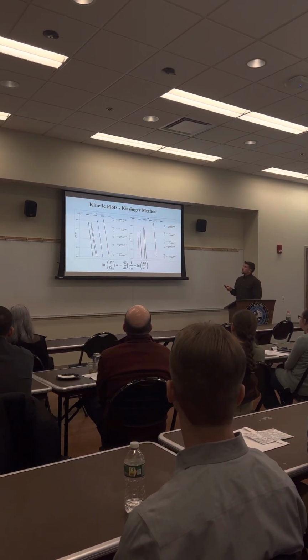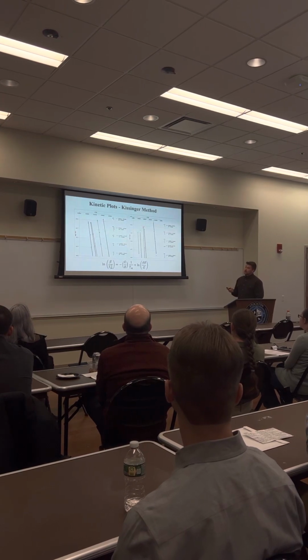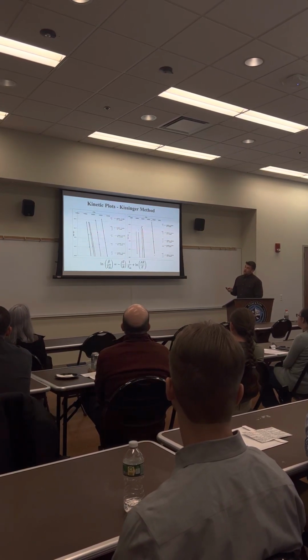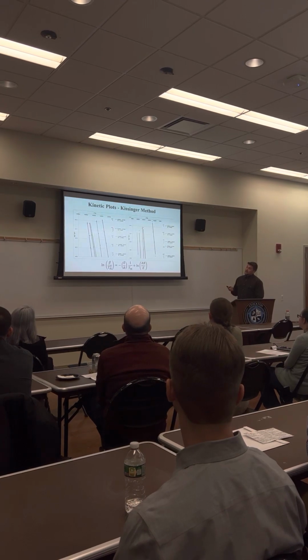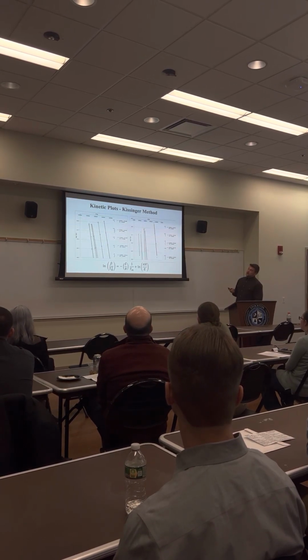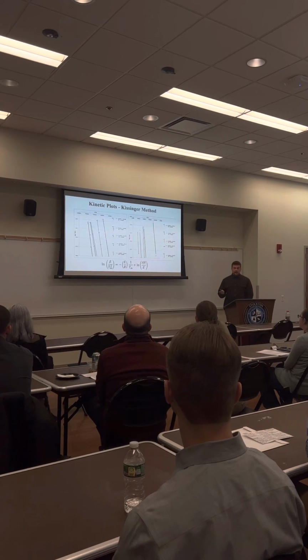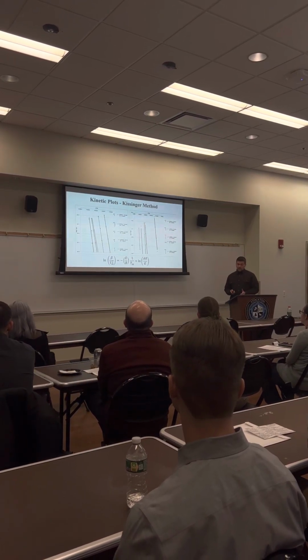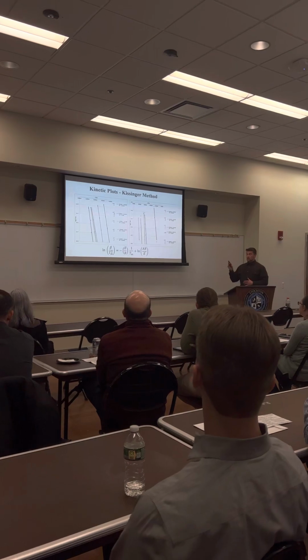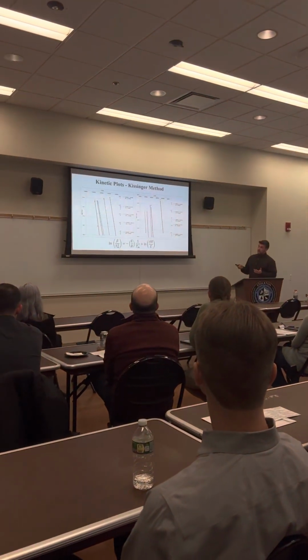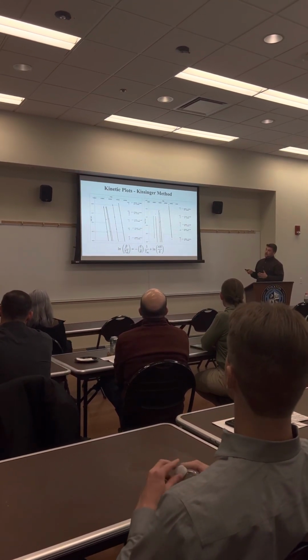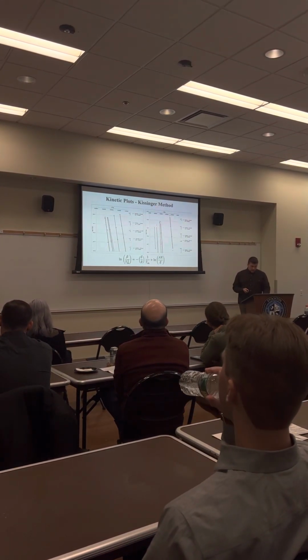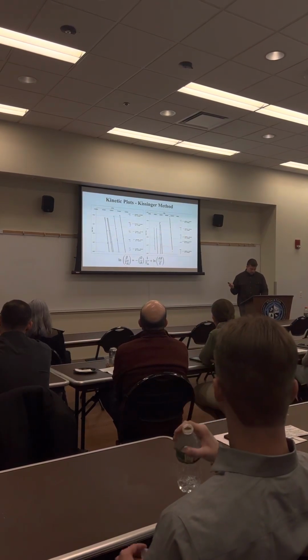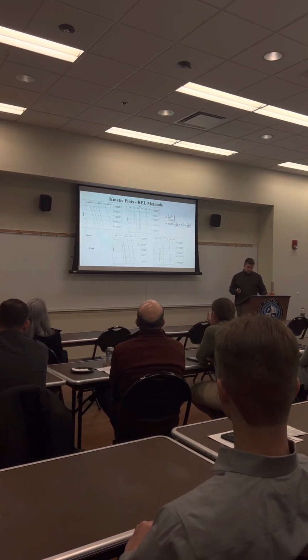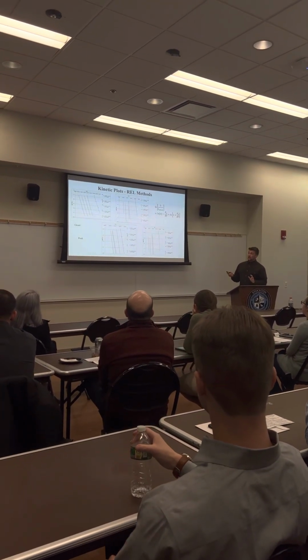So if you look at the R-square values for each, they're all pretty close to 1, meaning whatever we plotted, the 4 rates, fit on this line. If you wanted to, let's say, extend the line in either direction, you could get a good estimate on the behavior, or you could get the values from a higher or lower heating rate, given that it fits the line, and these lines are very close to 1. These are very small intentionally.